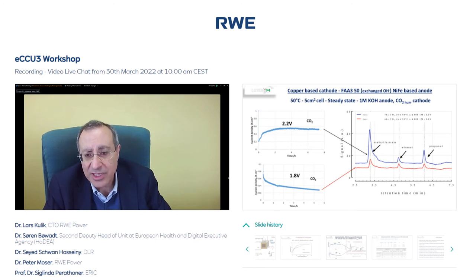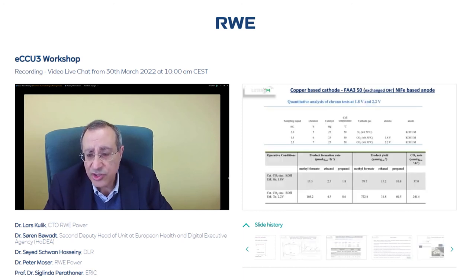Of course, we are happy with this high current density, but unfortunately, this does not correspond entirely to organic products, because you can see on the right plot that there is no proportional increase of the carbonaceous products by operating at a higher voltage corresponding to higher current densities. The large increase of current density is essentially related to the flooding of the electrode and the increase of the hydrogen evolution reaction. The main liquid products achieved in these tests are essentially methyl formate, ethanol, and propanol. But still, most of the products are gaseous, essentially hydrogen evolution.